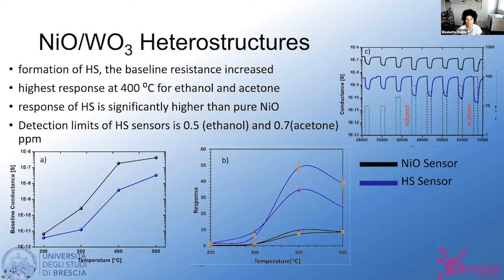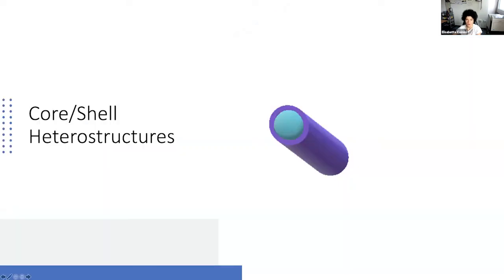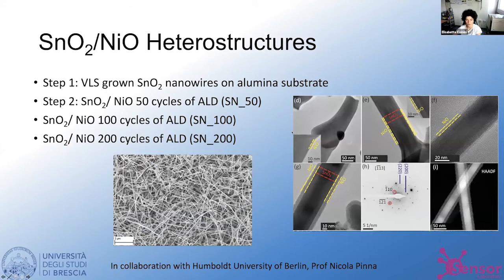And if you look at the response over the temperature, we can see that even in this case, we have an enhancement and a decrease in the detection limit of ethanol and acetone compared to pure nickel oxide. But this is not the only way in which we can do heterostructures. We can also have core-shell heterostructures, and this was done in cooperation with the Humboldt University of Berlin, the group of Nicola Pinna. We gave them our tin oxide nanowires, and they covered them with a small layer of nickel oxide on top.